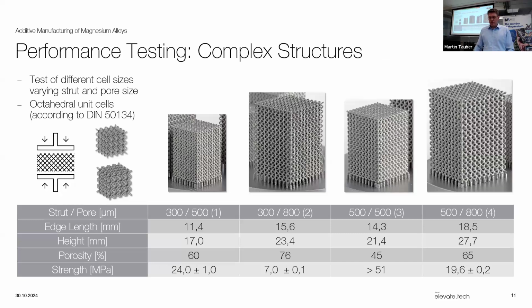The structures that we do and which we also looked at are mostly test specimens so far. I mean, we are also in applications already, but in this presentation, we mostly looked at test specimens. And here are some examples of how we can tailor the properties of these test specimens. So we can do different strut and pore sizes, so we can tailor the material to the needs that we have in a medical application, for example, to force cells to grow in, and also for the strength that we want to reach. And in this case, with a strut and pore size of 500 micrometers, we were able to keep over 51 megapascals, which in this case meant you can put 1 ton of weight onto this really small specimen.